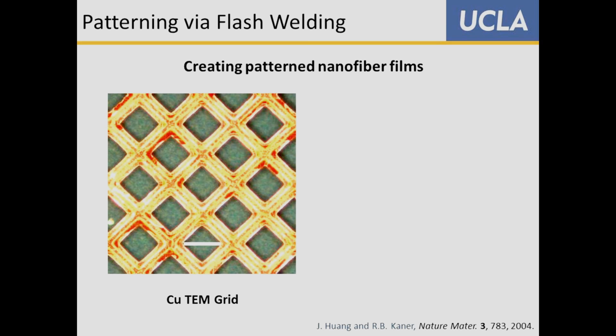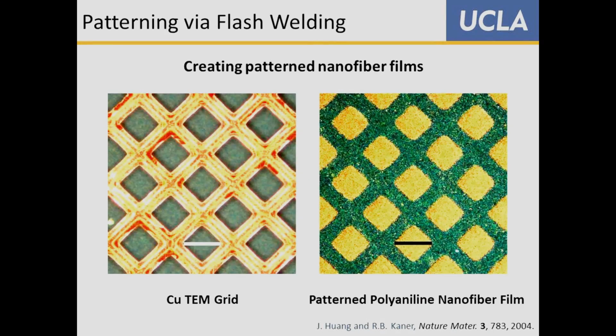So this is a copper transmission electron microscope grid, and this is the doped form of the polymer. It doesn't matter if it's doped or de-doped, but we like this because of the color contrast. So we hit this with a flash of light, and we remove the grid. Where the grid protected, it's still green and nano. Where the grid didn't protect it, it actually melted. And you can see the huge contrast. These are real colors.